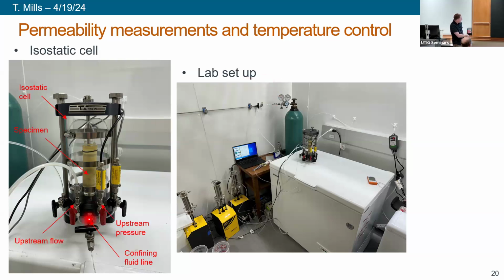And then we can use these ports down at the bottom with these red handles. These two are connected. One measures the pressure at the bottom of the sample, and the other one flows in our gas. So we're using nitrogen. And then it flows up through the sample, up through these lines, and comes out the top of the sample and out this downstream line. And then our pressure at the top of the sample is read at this other handle. And so this is how we're measuring the permeability.